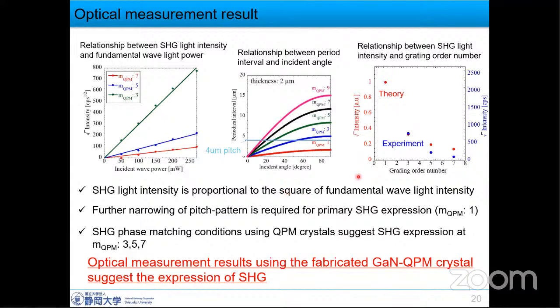So this figure shows the relationship between incident energy and peak intensity. SHG light intensity is proportional to the square of the fundamental wavelength intensity. This result and this one are theory and experimental data of the relationship between SHG light intensity and grating order number. So this result indicates that optical measurement using the fabricated GaN QPM crystal suggests the expression of SHG.